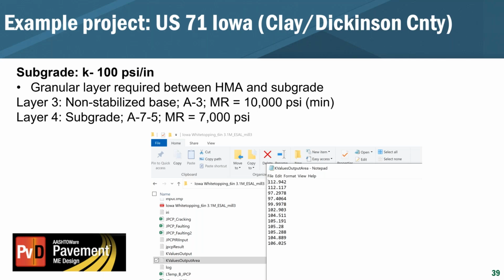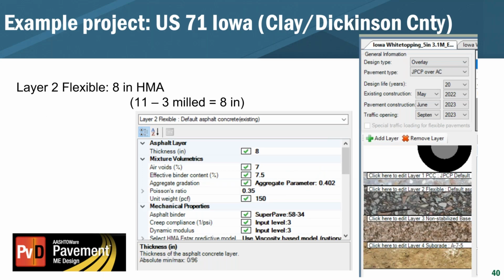This was actually my second guess at it. So you can iterate through. The first time the resilient modulus of the subgrade was a little bit too high, so I dropped that down to 7,000 PSI and got this. So again, the idea is that depending on the information you have, you can still use Pavement ME. You just might have to interpret the results a little bit to make sure that you're modeling the section that is actually out there.